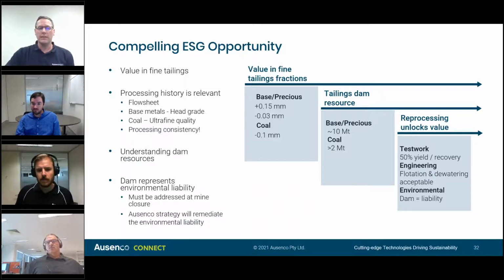So for the coal industry, there's typically valuable material or low ash product contained within the minus 100 micron fraction. This is important to grasp, that when a plant starts up without flotation and then later on adds in flotation, the previously discarded minus 100 micron material can be recovered from the tailings dam.